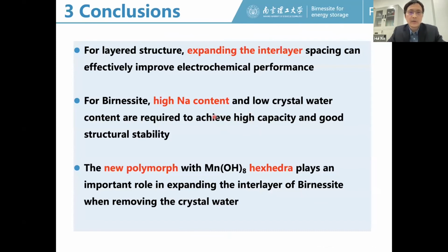Okay, so finally, there's the conclusion part. So first, for this layered structure, expanding the interlayer spacing can effectively improve the electrochemical performance. And for this Birnessite, we need high sodium content and low crystal water content to achieve a high capacity and good structure stability. And in this material, this new polymorph with this manganese-oxygen-hydrogen hexahedron plays an important role in expanding the interlayer of the Birnessite when removing all this crystal water.